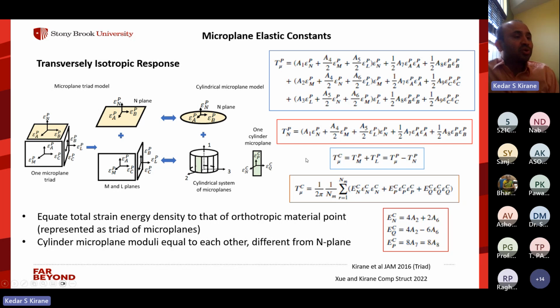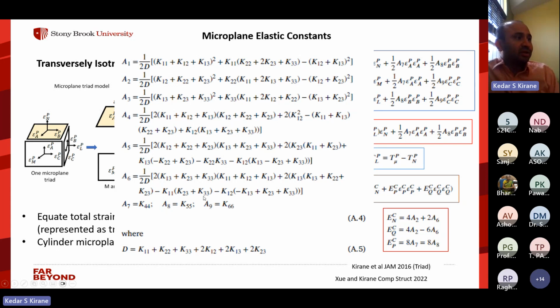And what you can then show is that the first row is the strain energy density from one of the planes, and the second and third are the other two planes. If you equate that to the strain energy density of the cylindrical system of microplanes, you can obtain the moduli which operate at the cylindrical level. So you can calculate the microplane level moduli, which are different from the material's elastic properties. But if you implement this as a cylindrical system and you homogenize it, you recover the transversely isotropic response of the composite. And again, to briefly show, A1 through A9 are the various elastic properties of the composite.